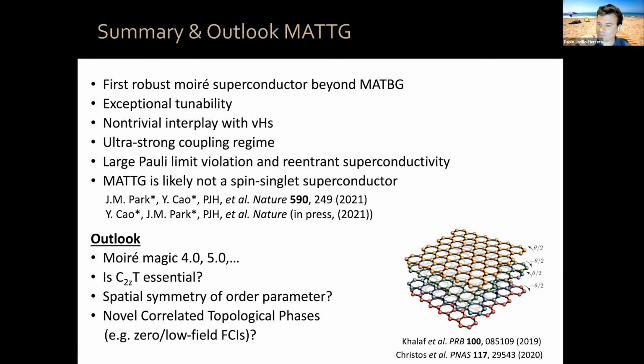However, recent thermodynamic measurements with our collaborators, Shahal Ilani, independently by us and also by other groups, have shown that when you apply an in-plane magnetic field, the magnetization of the system changes. With transport we did not measure directly the magnetization, but with our chemical potential measurements, we can measure directly the magnetization via Maxwell relations. We see that the system acquires a magnetization at a very small magnetic field very fast. So the system is either a strong paramagnet or a ferromagnet, okay? So now, more and more people are starting to think that the system at nu equals +2 may be a spin polarized system, okay?